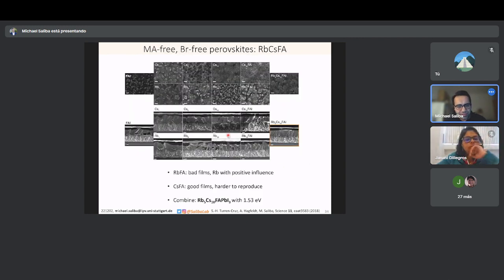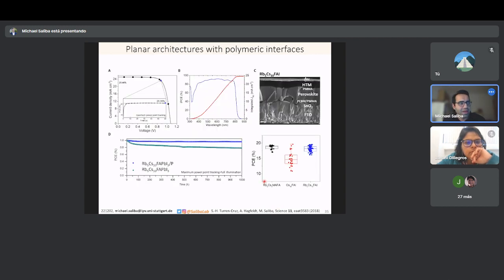Here we have some figures where we mixed the cesium FA together, the rubidium cesium as well, and we found that only a mixture of the two, rubidium and cesium together with FA, has both the morphology advantages, but also the advantage of high performance ultimately as well, with a low band gap at 1.53. And you see that here, we started making planar devices, which are very hard to make because you don't have the advantage of the mesoporous structure underneath.